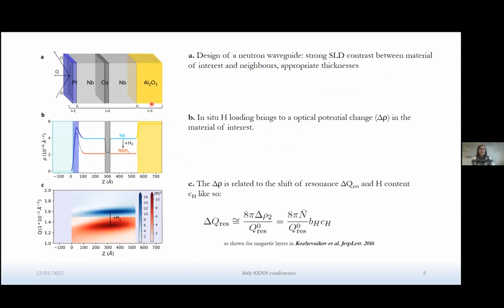So now let's see the case of our resonator. So our design of the sample. We have chosen as a layer of interest niobium, which is a material with an intermediate SLD, and it's a well-known hydrogen absorber. So in order to obtain the resonant enhancement, we have chosen as a substrate sapphire, and we capped it with a platinum layer, which both have a higher SLD, as you can see here in the SLD versus depth profile.